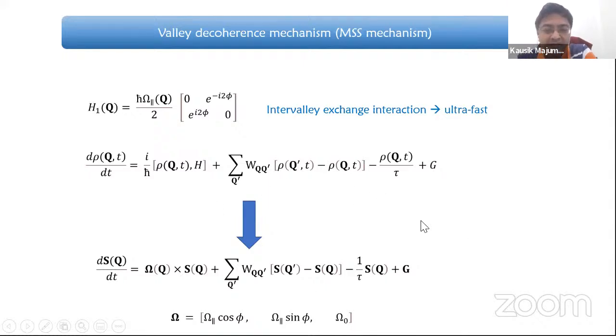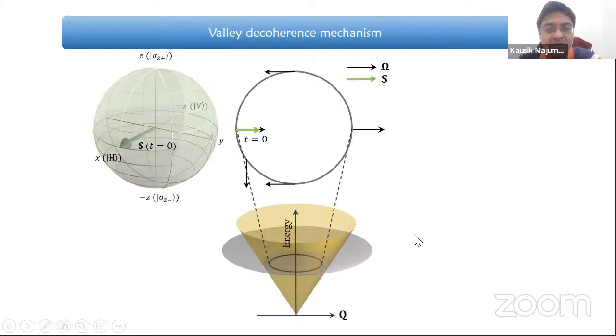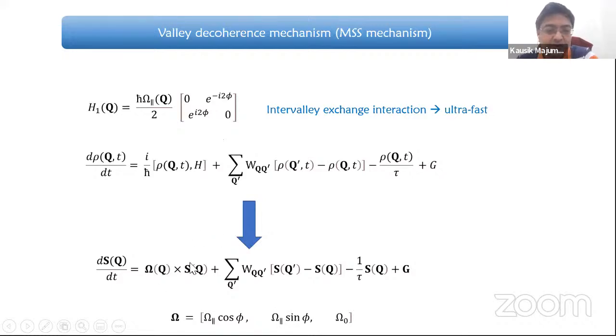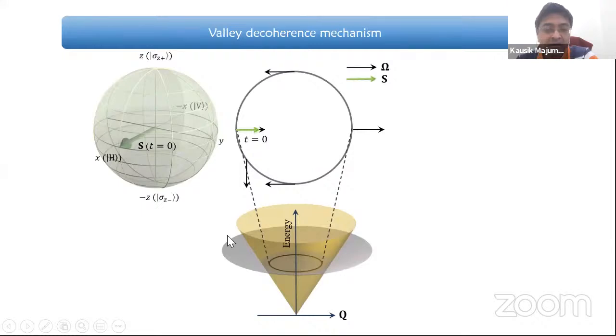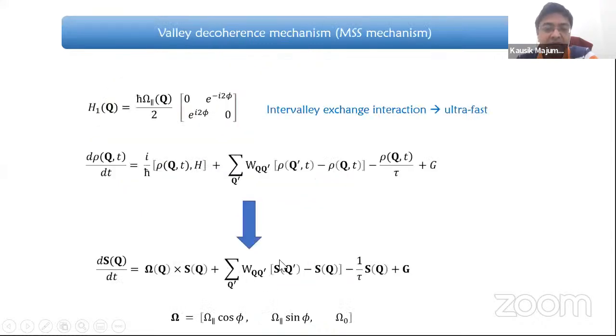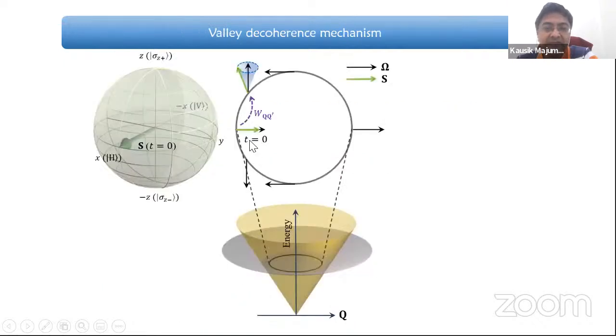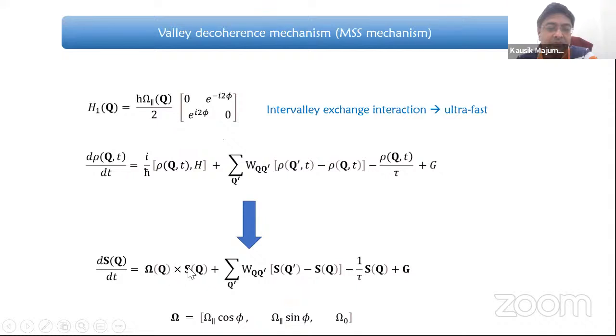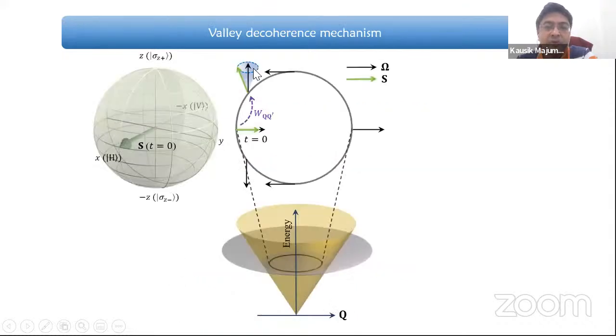To explain this equation pictorially, let's say you are generating some linearly polarized light at t equal to 0. Like I said, this cross product is actually 0, so nothing really happens. But then it scatters because of the finite scattering rate, to some other point in the light cone. Once that happens, the cross product is no longer 0, and it starts precessing around this vector. And this keeps on happening.